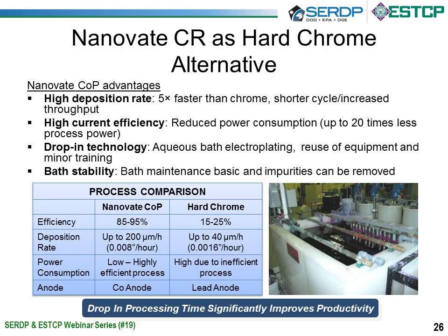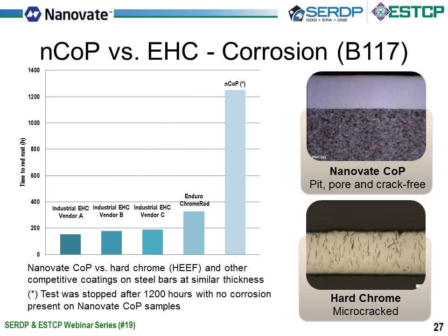It's a fairly simple chemistry, and it's very robust. In fact, the main process that we've had at Integran has never been replaced since its initial mix-up in 2004. So that's a very good demonstration of its robustness. And I have one slide here on the properties. One of the best properties is related to its corrosion protection compared to hard chrome.